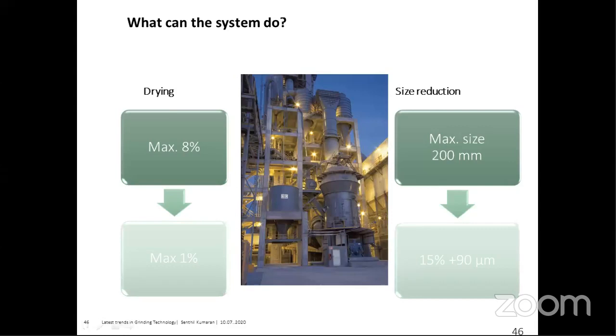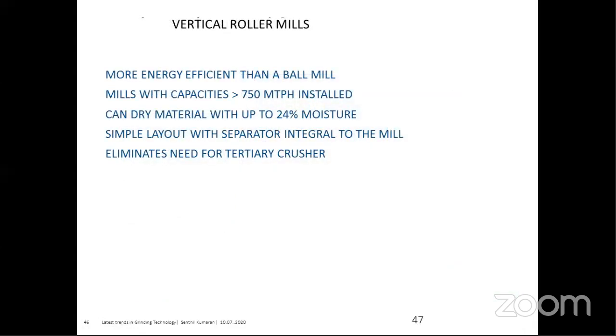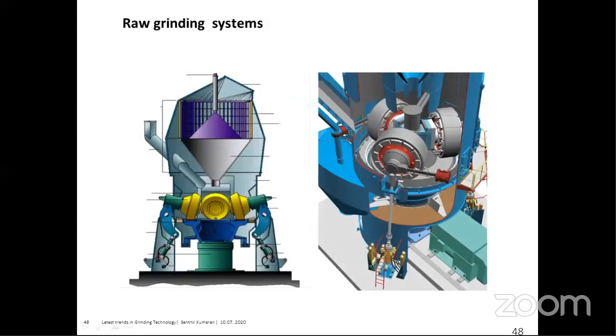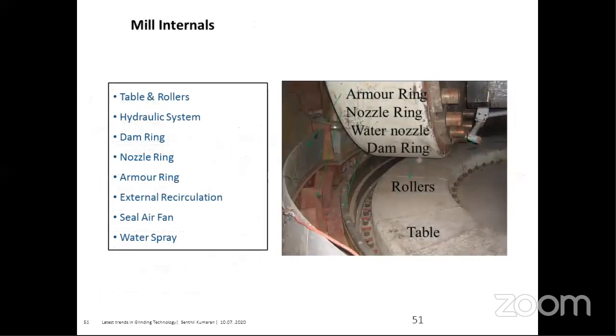So this is a typical vertical roller mill. For drying, it can dry up to a maximum of 8% moisture. For size reduction, it can reduce from 200 mm to 15% retention on 90 micron. This is more energy efficient. The capacity of vertical mills can be as high as 750 metric tons per hour, and in India, in one place we have 900 metric tons per hour mills also. It can dry the material, it has a simple layout, and the separator is integral to the mill. So this is a typical raw grinding system, which we have seen already. This is the mill internal.